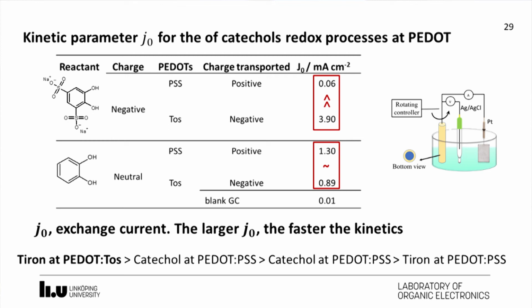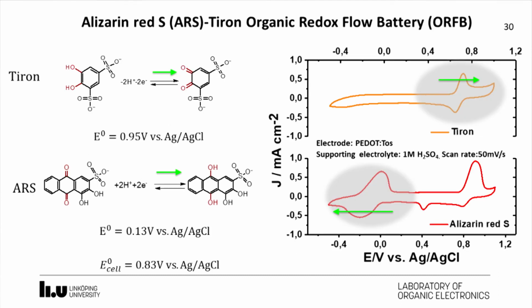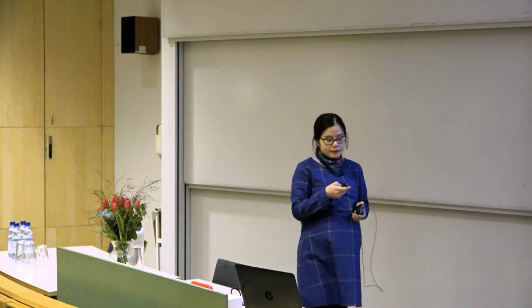So to summarize, we have shown that tiron redox at the PEDOT:Tos has the highest electrocatalysis, followed by the others. Keeping this insight, we picked two negatively charged molecules, alizarin and tiron, for the organic redox flow battery measurement. Tiron was used as the posolyte because it has a relatively high redox potential. Alizarin was used as the negolyte because of its low reduction potential. Together, we are supposed to get 0.8 volts from the batteries.